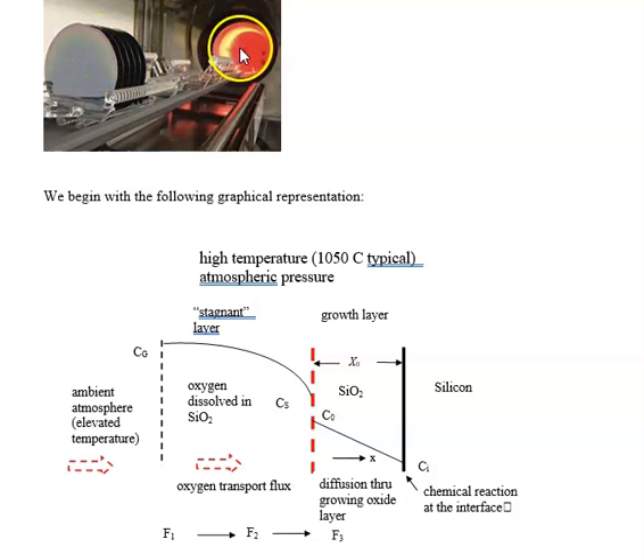So once the wafers are in the furnace, we are in this region here, and this region is basically we call it the stagnant layer. It's oxygen, which is dissolved in liquid SiO2. There needs to be a concentration gradient which drives the oxygen from purely atmosphere to this layer right here, where we start the actual growth layer of SiO2. This is glass. This is solid SiO2.